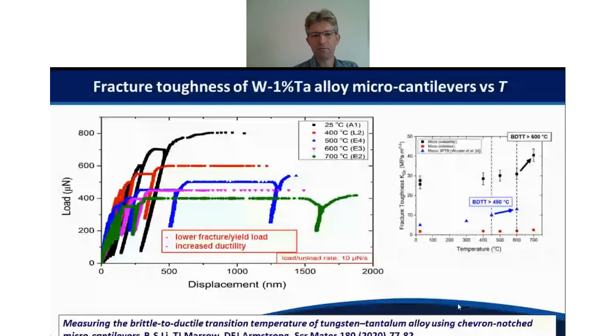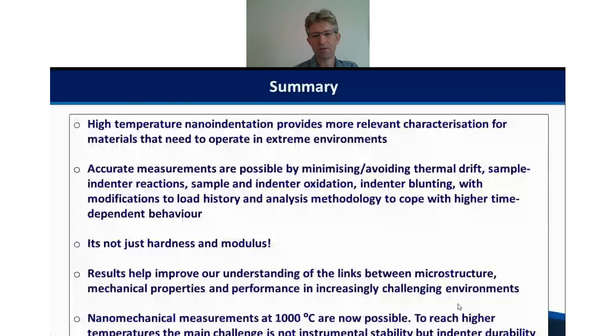Another more recent example from the University of Oxford, in this case, Bo-Xuan Lee and Dave Armstrong have been looking at multi-cycle tests as a way to pull out fracture toughness, in this case on machined micro cantilevers of tungsten with 1% tantalum in there. And if you see on the right, they're able to quite nicely pull out differences in fracture toughness that relate to the onset of the brittle-ductile transition temperature.